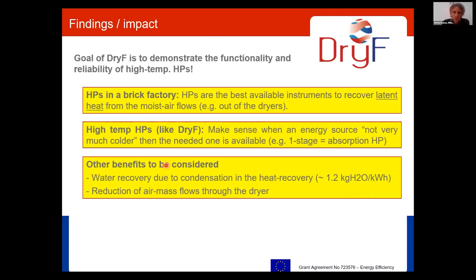And what we also have to think about are other benefits when we do this wet air condensation, in that we do water recovery. This is not important in Austria, but when you look at facilities in Italy and in Macedonia and wherever, water is an issue. And we have to be aware that for 1 ton of fired product, we have to evaporate more than 250 kilograms of water. And we talk about around 300 tons per day of product. So this is a lot of water we could recover. And it's demineralized, so it's of high quality.